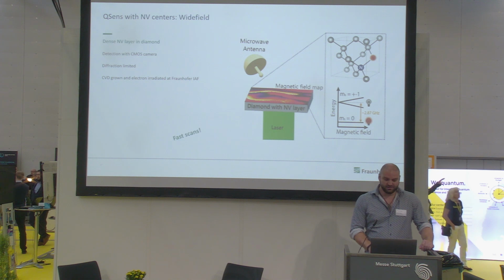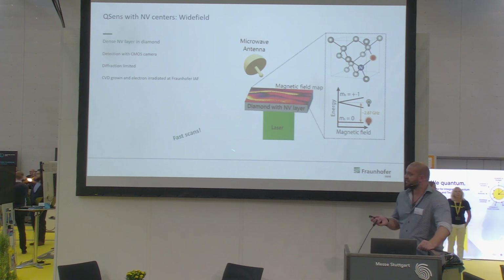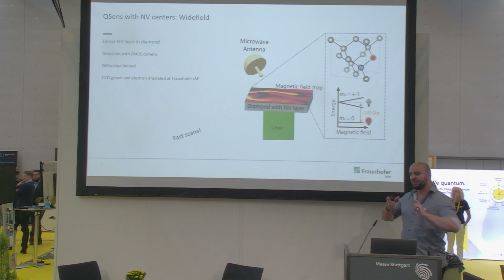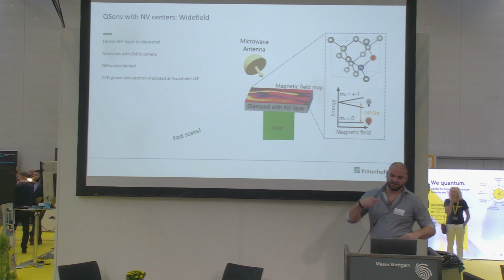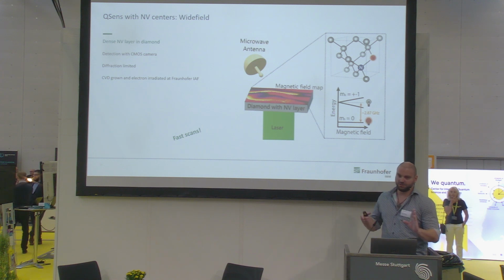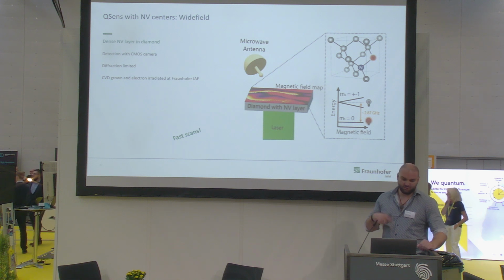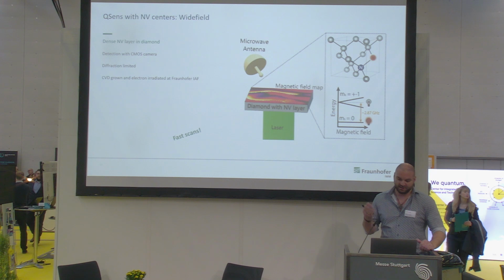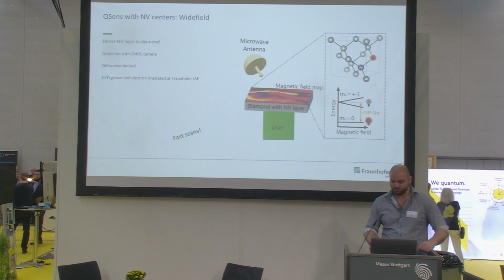So the big advantage we get from this is fast scans. With this wide field setup, we sacrifice a little bit of resolution, but we get a scan on the order of 250 by 250 micrometers in like 15 minutes. Which is orders of magnitude faster, of course, than the scanning approach, but we sacrifice the resolution.